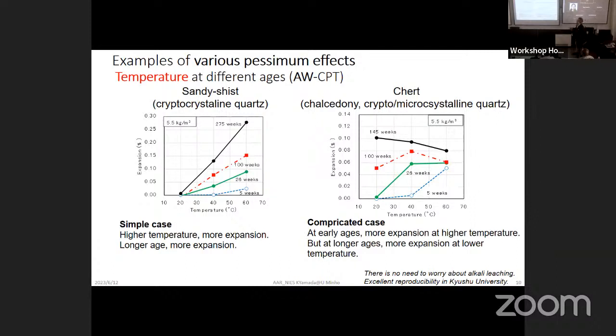Then I talk about the alkali threshold. Please look at this figure. This is a case of sandy schist. The reactive mineral is cryptocrystalline quartz. This figure shows the temperature dependence of expansion at different ages. So this is very reasonable or simple. At higher temperature, expansion was accelerated, and at longer age, more expansion. This is a very usual case.